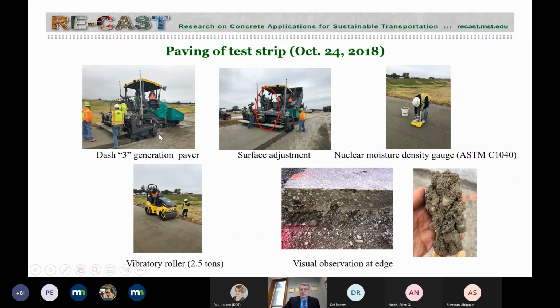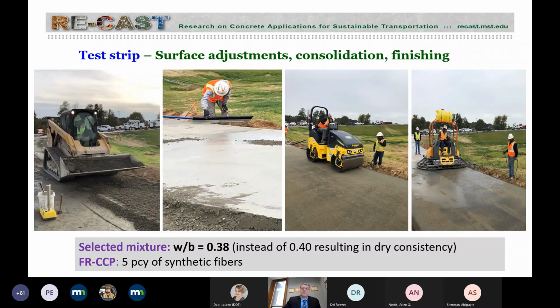And in some cases, especially near the edges where we did not ensure good consolidation, we really had a crumbling structure. So all of that was used for adjustment of the placement parameters and the consolidation parameters. So this is the test strip, and you see in some cases there were adjustments and hand finishing. A lot of trials, we learned a lot from that.